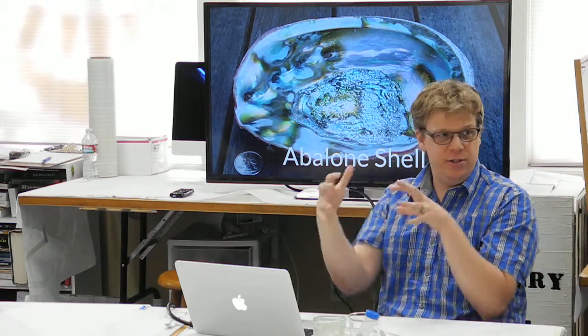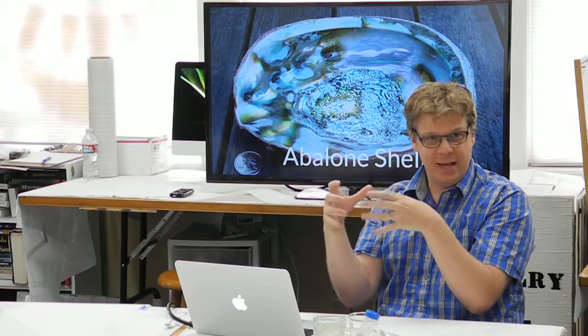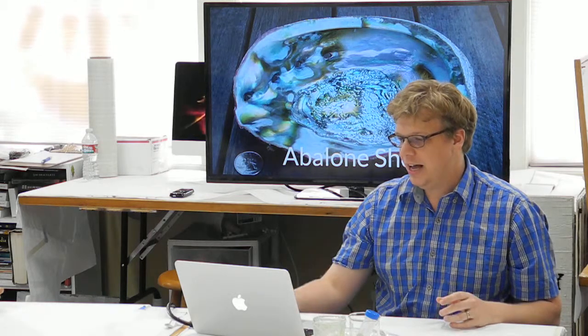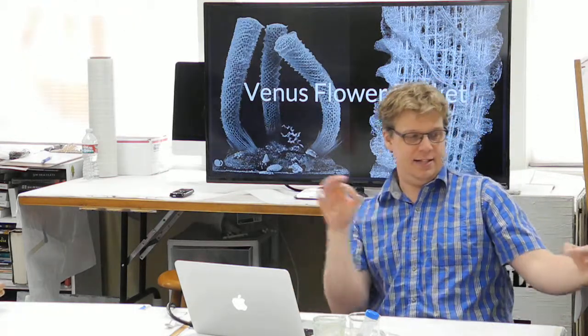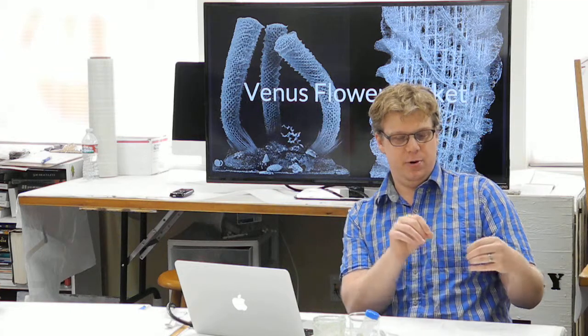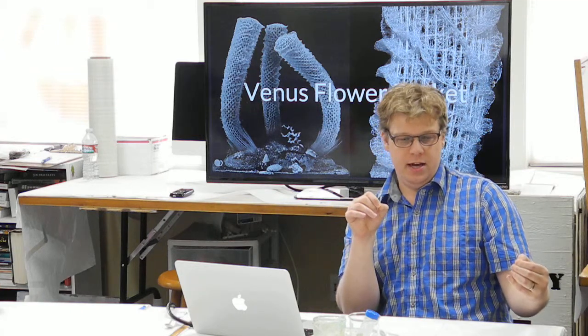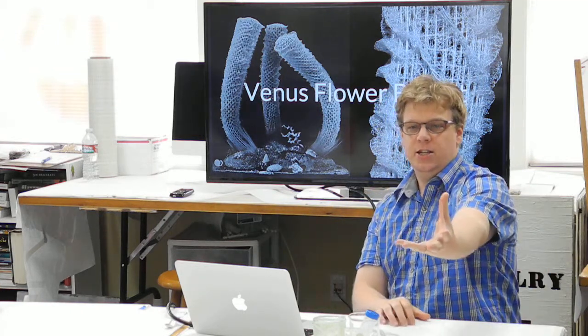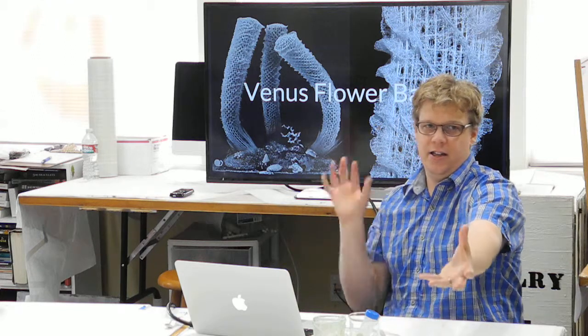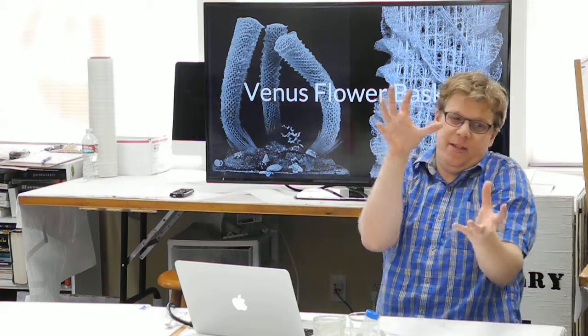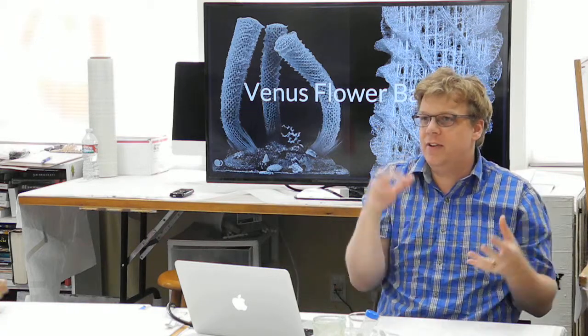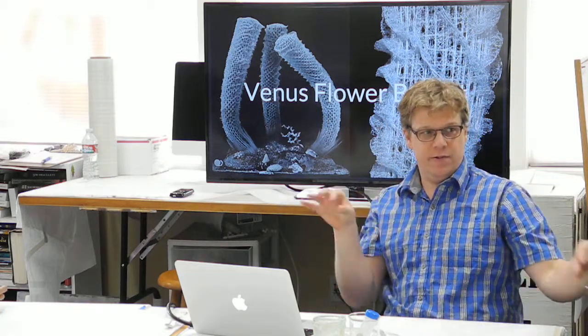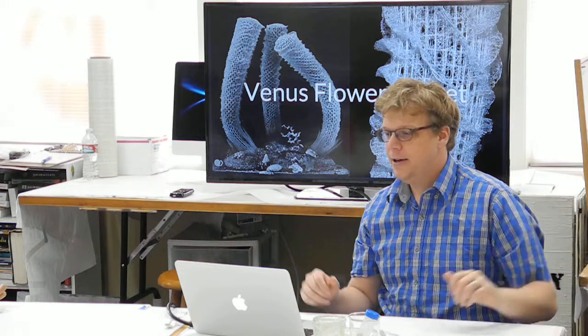You have proteins that will literally do different tool tasks to that brick to get it to the shape that it uses to then stack. The way that the glass one works is it makes this protein thread, and then it literally takes the precursors of glass, the silicon and the oxygen atoms, and puts them in the right position to form glass right on its surface. It does that throughout the entire surface, so it basically coats itself in glass.